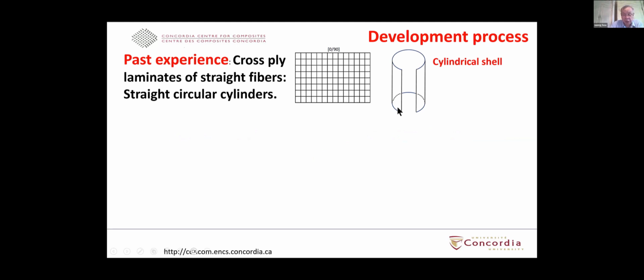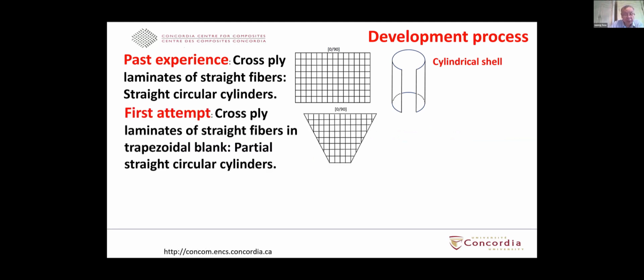Then in the case of if you want to make something like a cone, we thought initially that maybe we just use the same kind of straight fibers, except we cut the edge. We have the edge here that has some kind of a shape of a trapezoid, and maybe that'll give you the shape of a cone by the time you cure and cool it.